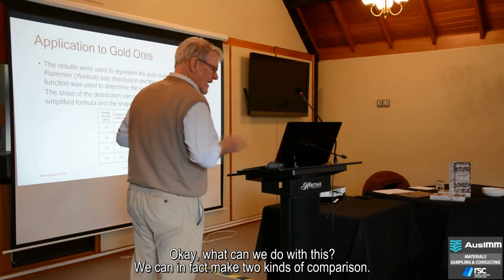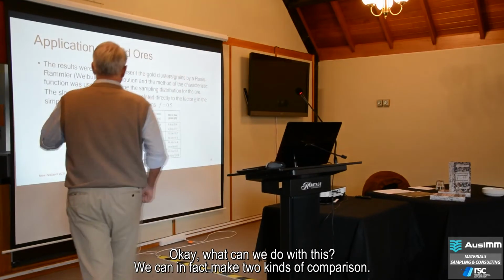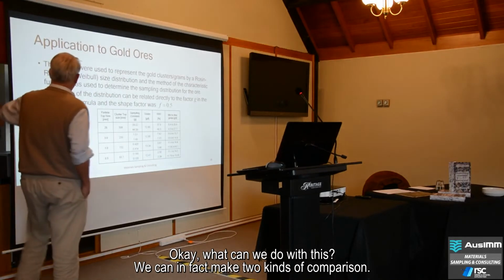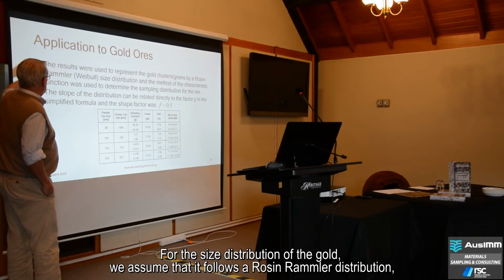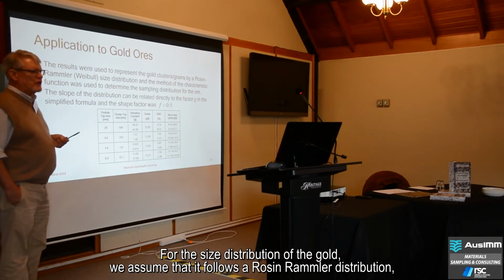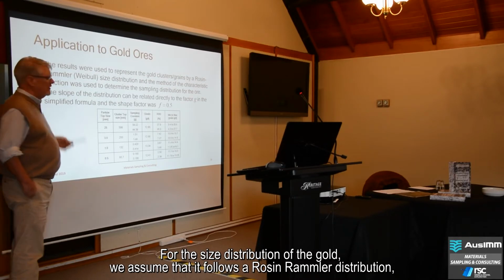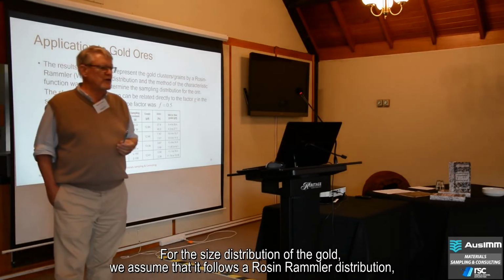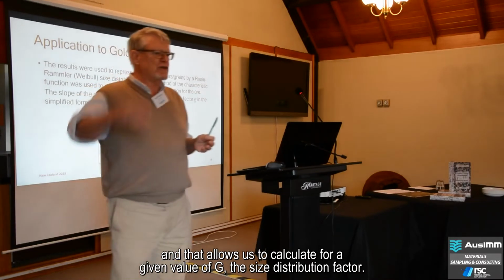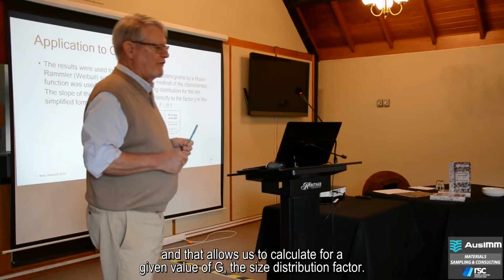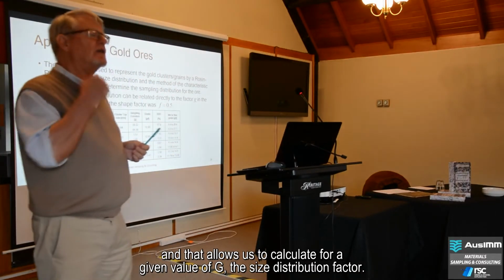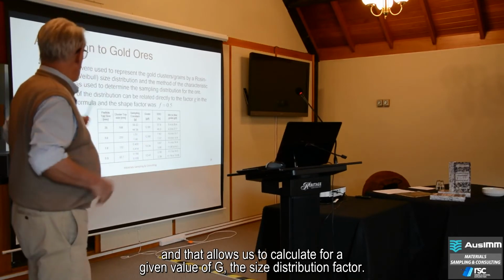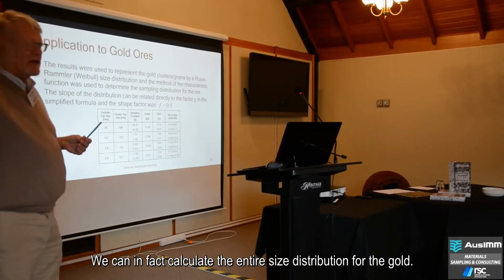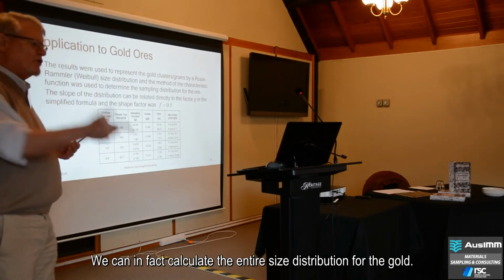We can, in fact, make two kinds of comparison. For the size distribution of the gold, we assume that it follows a Rosin-Rammler distribution, and that allows us, for a given value of G, the size distribution factor, to calculate the entire size distribution for the gold.